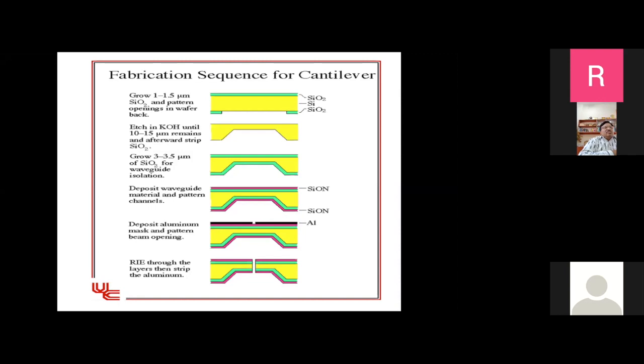So you etch out a small rectangular or circular region, or a slit type of region in the wafer on the bottom side. Then you use a chemical etching, very dilute KOH can be used for etching out that pattern. You can call it a diaphragm, like a tabla surface. Okay, so this is quite thin. Depending on your design and the force that it has to take, you can make it as thin or as thick as possible. Typically it is of the order of a few tens of microns, let me say 20 microns is a typical example.